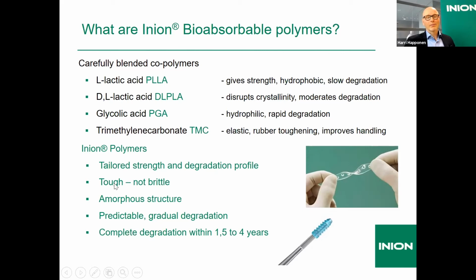We can make the implants tough, not brittle, and they always have amorphous or substantially amorphous structure, meaning that water is able to absorb everywhere in the implant and degradation is complete. We can also guarantee that the degradation is predictable and gradual, and then happening in around 1.5 to 4 years. In average, it's around 2 years.